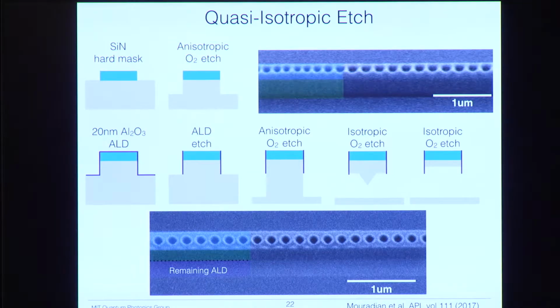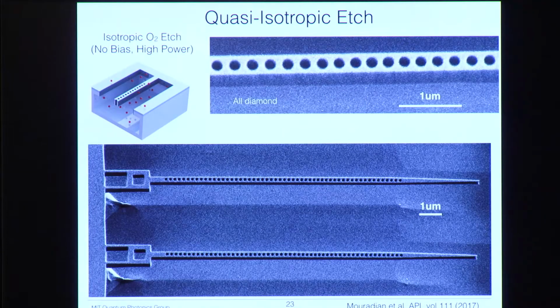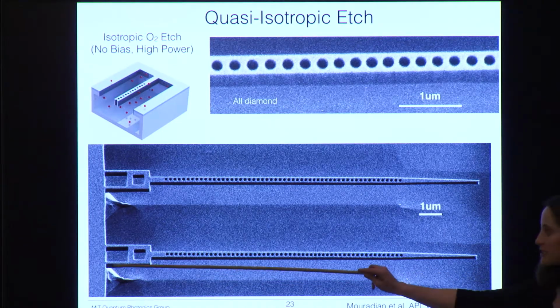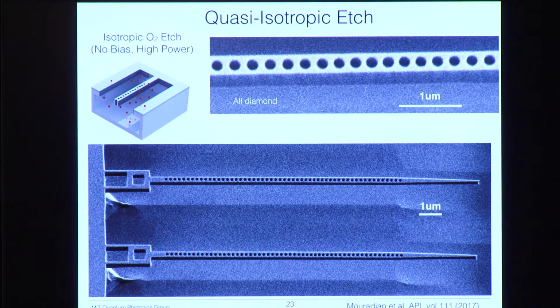And then, so it continues, it's rectangular, and then we take off all the masks with HF, and we see a nice rectangular cross-section, and we can create very large, totally suspended structures. And luckily diamond is very hard, so we can actually create even longer than this. This is, I think, about 10, maybe 15 microns, but we can create, and Noel's done a bunch of this, huge structures that are fully suspended. And this is also only suspended on one side. And these are only 50 nanometers, just to give an idea.